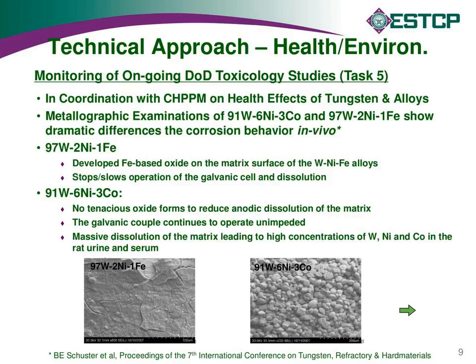But after 6 months, all the rats that had been embedded with tungsten nickel cobalt, which is one of the major alloys that's out there, all of them had nasty tumors, had metastasized to the lungs, and they all had to be destroyed within 6 months. They were usually showing signs within 3 months.